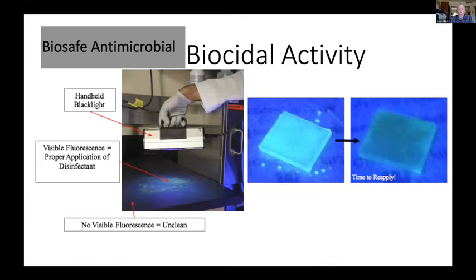You can tell very easily by putting a black light over the sample: if it's active, it will glow, as shown here in the center. When it has been used up or destroyed by one means or another, the fluorescence goes away. And so you have a way of telling if your material has coated a surface or not. As you can see here, you form a very nice uniform coat when you introduce a solution of this polymer or oligomer onto the surface, and you have a nice active surface for antimicrobial activity.